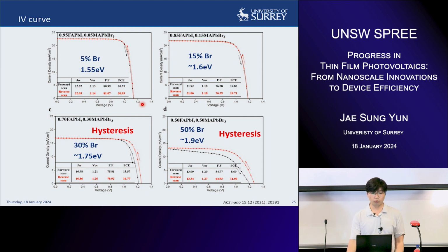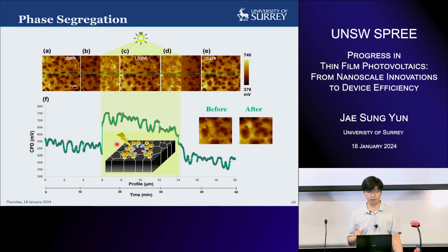Also, we put in more bromide, up to 15% bromide. There isn't much hysteresis. In halide perovskite, you can see some of the samples having IV hysteresis, and this hysteresis appears when you put in 30% of the bromide. So if you have a wide band gap, you obviously have a large hysteresis due to the ion migration. This is also linked with phase segregation.